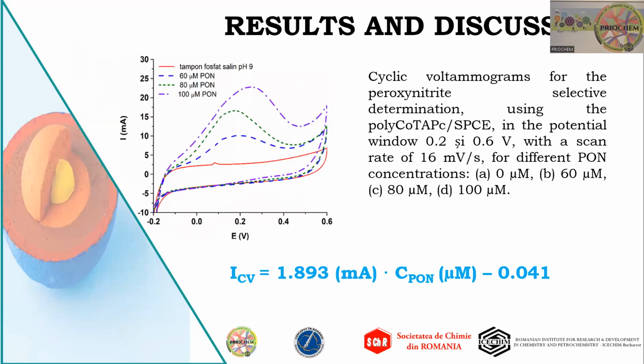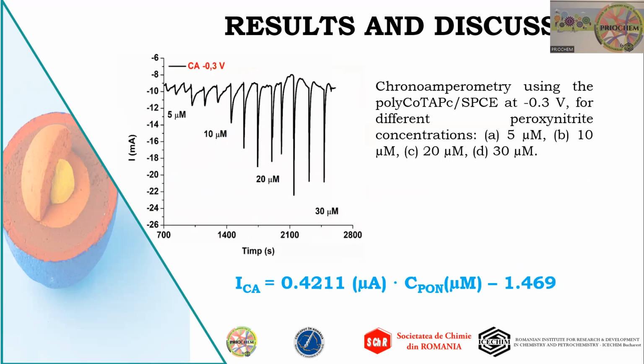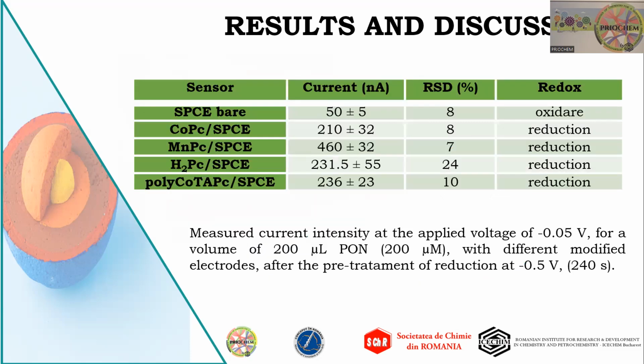and we had no real influence. For the calibration, I have chosen cyclic voltammetry in the specific range with different concentrations. I have them in a calibration curve, and I have also chosen other methods, more sensitive and more precise ones, such as chronoamperometry, with the same sensor presented at minus 0.3 volts, for example, in this case, and I calibrated the sensors.